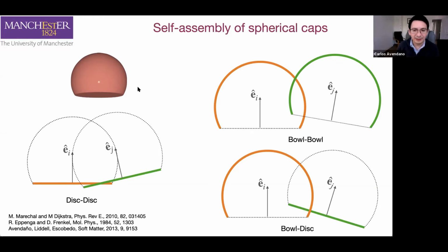And the reason why we did that is because the individual overlaps between disk and bowl have been reported before. Dan Frenkel reported many years ago the overlap between 2 circular disks, and it's a very efficient algorithm. The overlap between 2 bowls has been also reported by Marechal and Dijkstra. And Fernando Escobedo and I developed the overlap between a bowl and a disk. And between a bowl and a disk with a hard wall, well, it will be very similar to the bowl and the disk as well. So we have all the elements for the model.